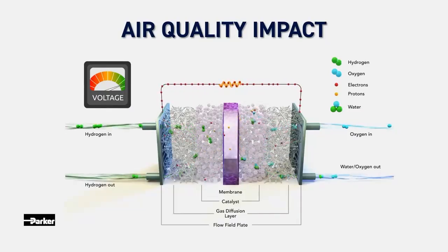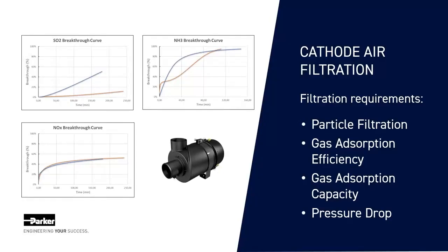There are different types of filtration technologies that need to be combined for optimal air filtration. To protect the stack, a cathode air filter is required. There are several filtration requirements which need to be considered when selecting such a product. Particle filtration is important. We need to make sure that all the particles are removed from the environmental air because this can block the gas diffusion layer and can also damage the membrane. The gas adsorption efficiency shows how well the filter can remove certain gases. The gas adsorption capacity shows how much of these certain gases can be filtered out by the product. The pressure drop is also important because this will impact the performance of the compressor.